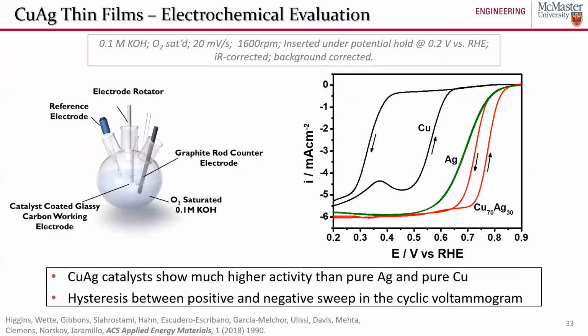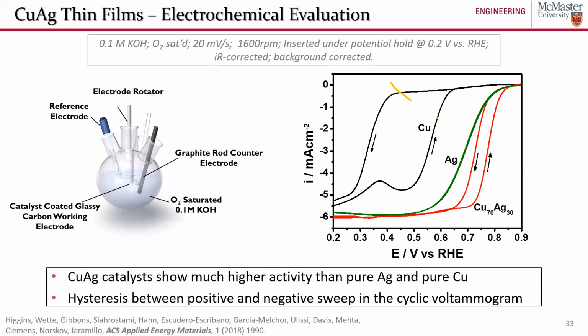That's not really the point, though. The point is that when we tested them for their electrochemical oxygen reduction activity in KOH, we found that the copper silver mixed metal thin films significantly outperformed pure silver. And pure silver is one of the best known oxygen reduction catalysts in alkaline electrolyte. And so essentially, if you've never seen one of these oxygen reduction polarization curves, anything that is to the right and down on this axis means a better catalyst.